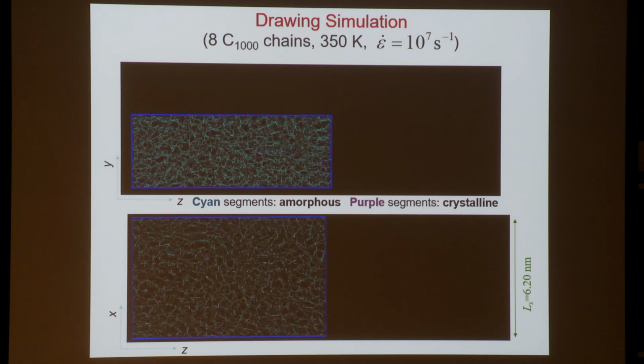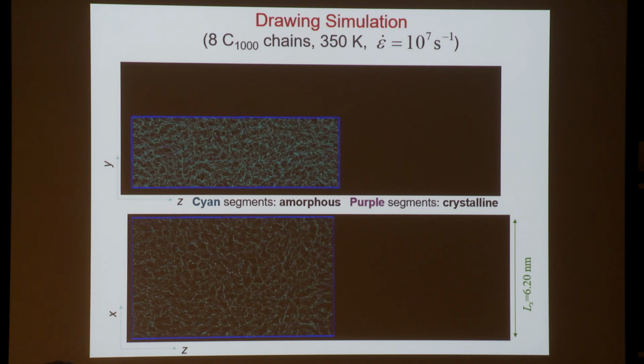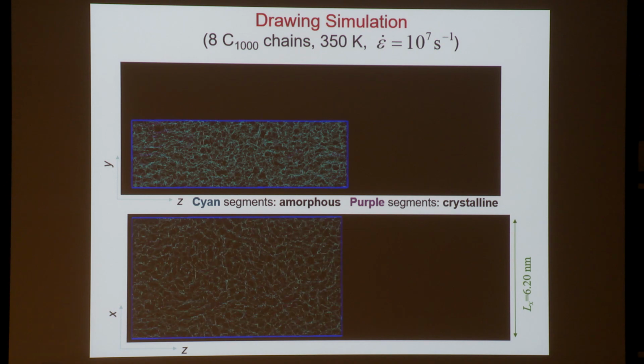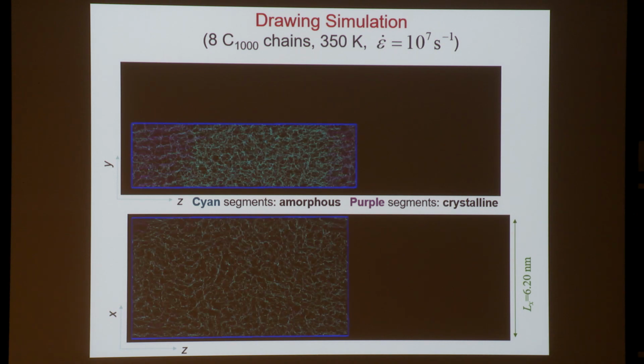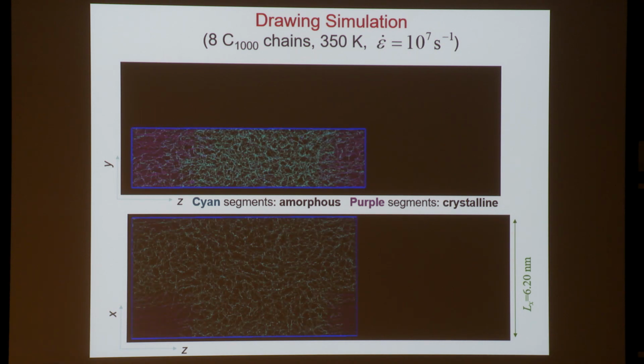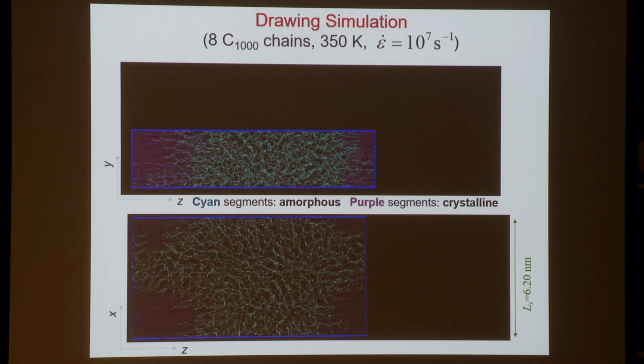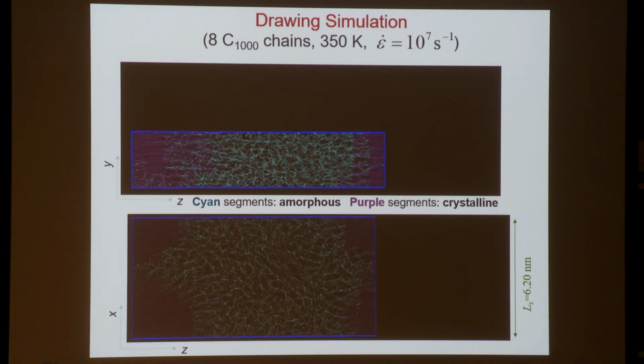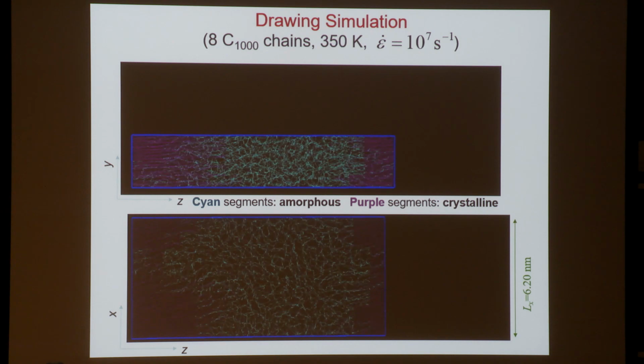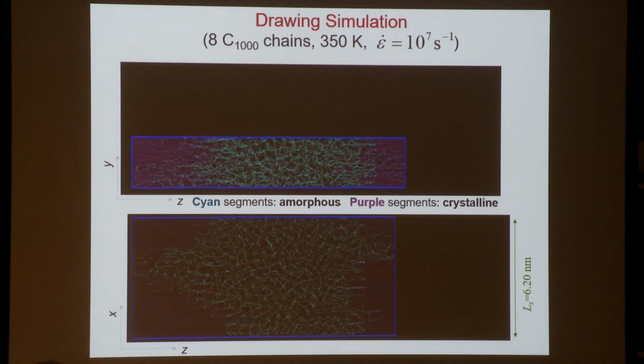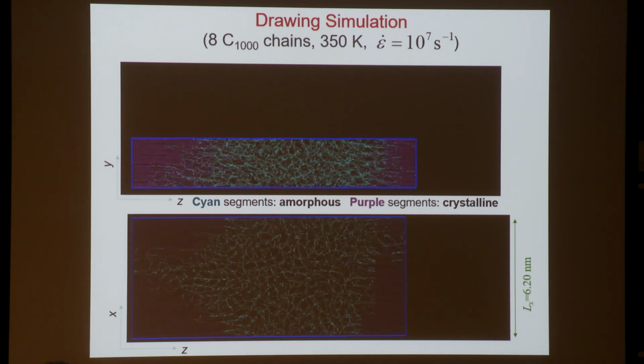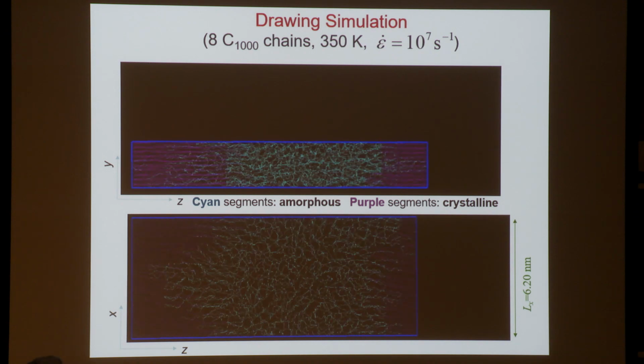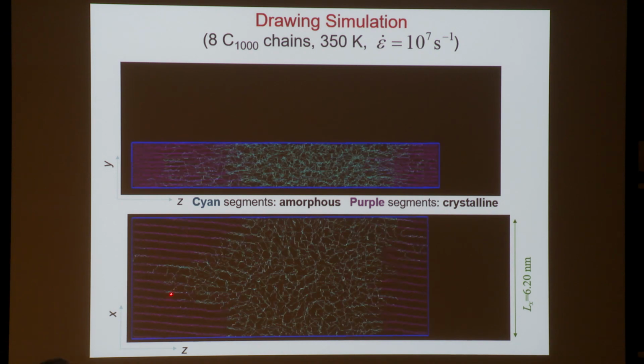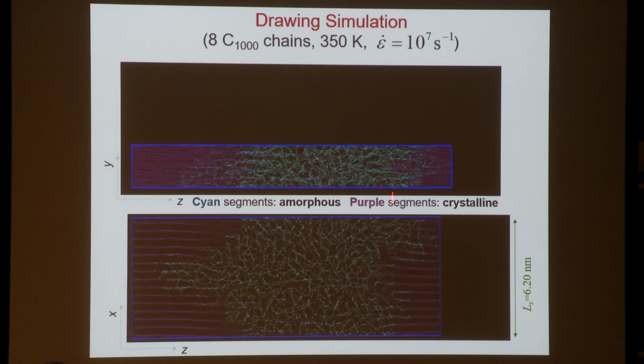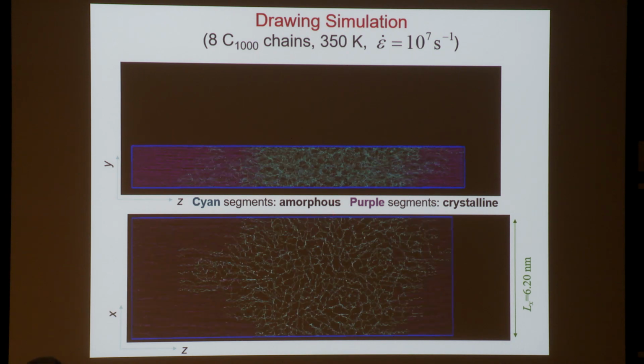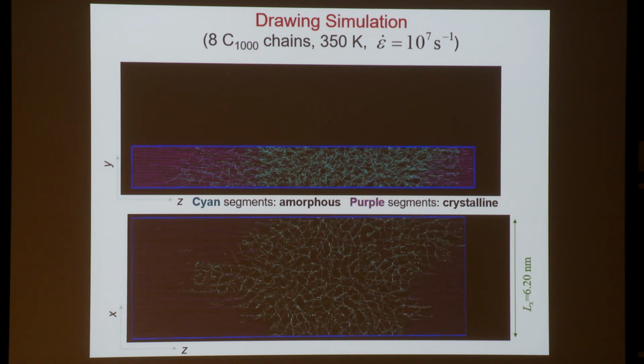So we will see that an ordered phase, an ordered nucleus appears and rapidly spreads through the system. And since the system is very small, here it is, the nucleus, the growth process ultimately percolates the model system in both the X and the Y direction. So finally, one gets a semi-crystalline morphology where one has lamellae, like this one and this one, and in between one has amorphous material.